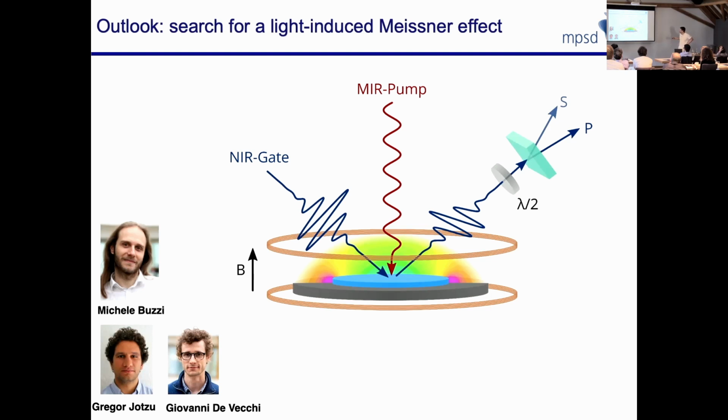This is a coil that generates a magnetic field. So we want to do an in-field excitation experiment, the equivalent of an in-field cooling experiment. What you want to see is not that B dot is 0, because you know that already from the optical properties. You want to know that B is 0 in the constant field. And so B threads the superconductor. This is a magneto-optical material, like a garnet.